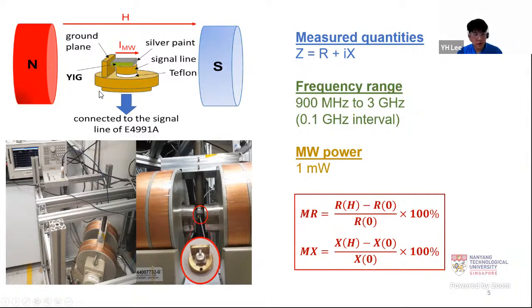The purpose of doing this is because when we connect this to the measurement setup, it allows the MW current to flow along the silver surface from the signal line back to the ground. Throughout the whole measurements, we ensured that the electromagnet field and the transverse magnetic field that's being provided by the MW current are always perpendicular to each other, which is a favorable configuration of FMR setup. The frequency range we measure is 900 megahertz to 3 gigahertz at 0.1 gigahertz interval with very low power to avoid any heating.